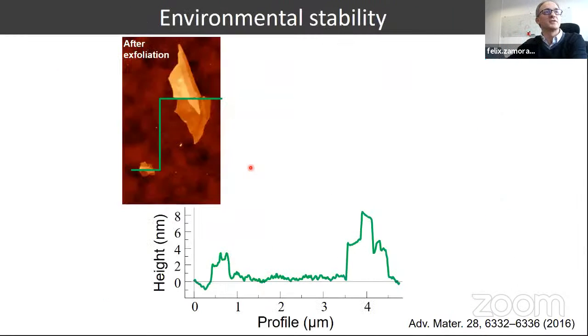Okay, so additionally, we confirm that our material has nice environmental stability. Let me show you this experiment. Here we have the two initial layers immediately after exfoliation. We took a height profile along this green line, and we allowed this substrate to stay for 2 months under ambient conditions.